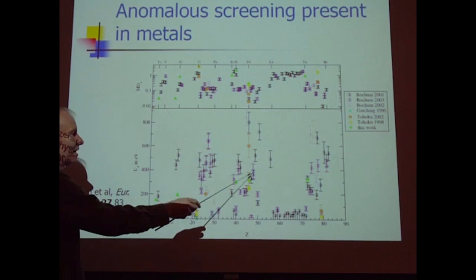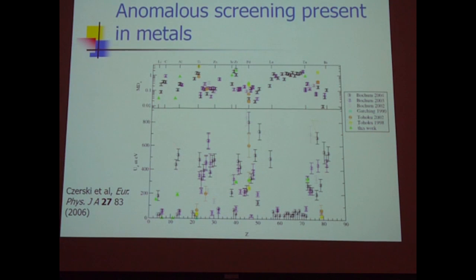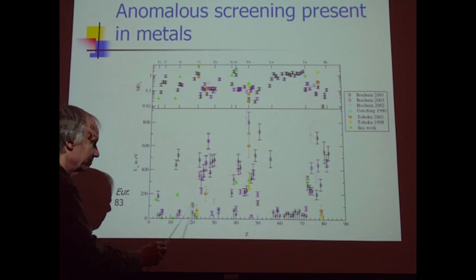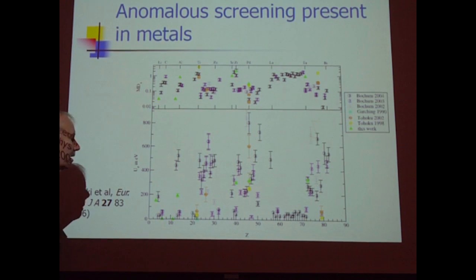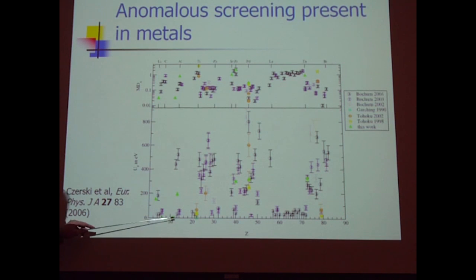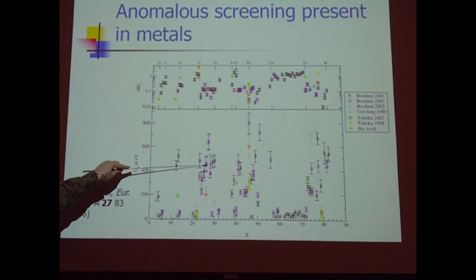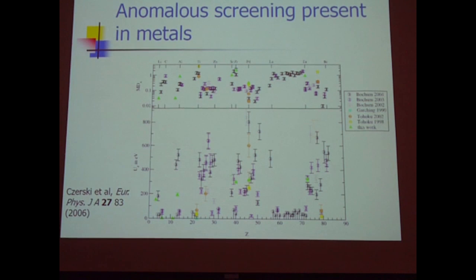Folks in the literature kind of think that, well, there's more experimental data points around 400, so the screening energy ought to be closer to 400. The theory, if you do Thomas Fermi screening, there are some calculations that show that you'd expect the screening energy to be close to 130 electron volts, which would be sort of down here. If we look at nickel, nickel's here. Nickel's got screening sort of a little bit like palladium. There are other metals that screen as well. These points are for the loading that was achieved in the experiments.